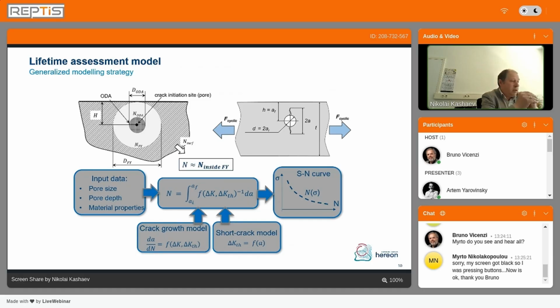And in principle, we need to calculate the number of cycles required for the crack to propagate in the fish-eye area. For every fatigue life prediction, one of the most powerful approaches is to do it based on fracture mechanics. If we consider the fracture mechanics-based approaches, in principle, we need to know the fatigue crack growth law, and if we know it, we can integrate and calculate the number of cycles required to failure of the component. In principle, the number of cycles from the initial crack length, our initial pore, until failure if the crack grows to the surface.